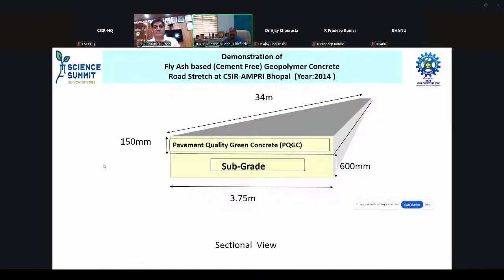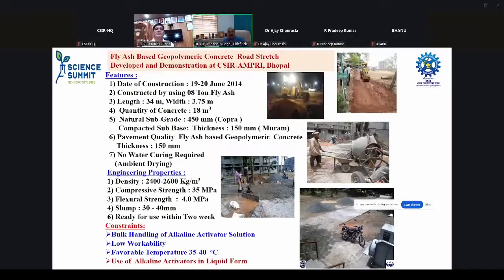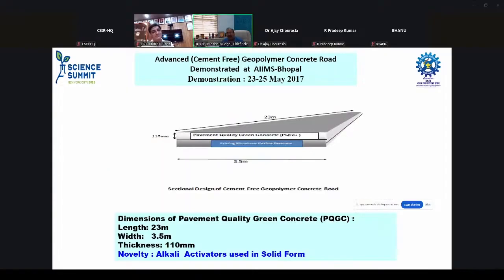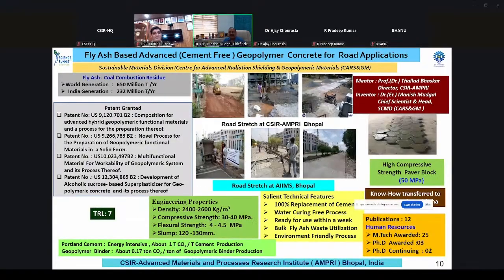We demonstrated a geopolymeric concrete road in our CSIR AMPRI premises in 2014, 34 meters long and 3.75 meters wide, with 150 mm PQC. We used around 8 tons of fly ash and developed this concrete with a compressive strength of 35 MPa and flexural strength of 4 MPa. In the first experimentation, we could reach a slump of only 30 to 40 mm, so it had low workability. Then we modified the process, and in 2017 we demonstrated this geopolymeric concrete